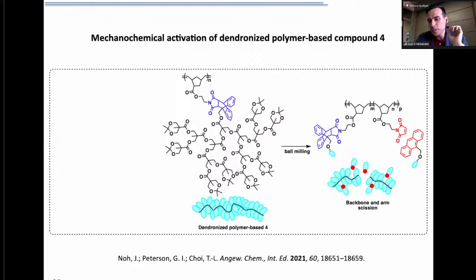Whereas when the reaction was carried out by ball milling, here you see also the cleavage of the backbone, but in this case, you can see the activation of the mechanophore, meaning that you can do the same by both techniques, but ball milling could also bring you something else. So they complement each other. And this is quite important. The reasons why they are working differently were related to the difference in which the activation occurs in solid state, because the ball milling experiment was done in solid state, whereas the sonication part is done in solution. So the differences in how the force is transduced and the lower mobility that you would have in solid state might have directed the reaction towards the activation of both the cleavage of the backbone and also the arms.